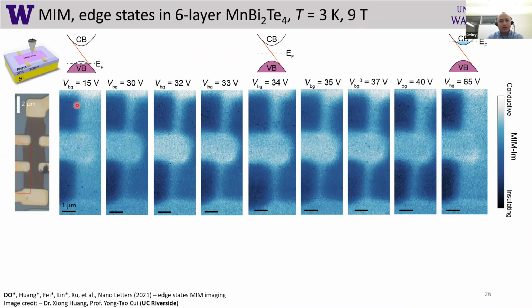And what we can see is that when we walk through the band structure from the valence band to the gap, in the gap we see essentially these white edges. White means that the material is locally conductive, and you can see that the inner part of the material is insulating. So we can essentially visualize these edge states. And one would wonder if these edge states are indeed chiral edge states.